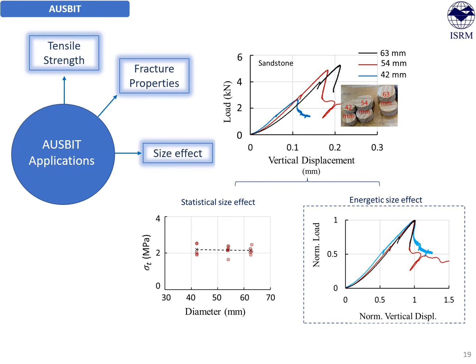of the disk specimen increases, which will result in an increase in the strain energy stored in the disk specimen. At the same time, the fracture energy requirement also increases, but that increase corresponds to the fracture surface. Now the difference between these two energy requirements, that is the strain energy stored inside the disk specimen, which increases with volume, and the energy required to cause fracture in the disk specimen, that is the diametrical crack, which increases with crack surface, results in the variation in the post-peak snapback response that corresponds to the energetic size effect, which thanks to AUSBIT we can now capture.